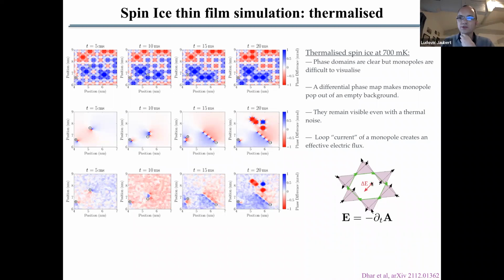To come back to Andre's question at the beginning, the magnetic charges are present, but the emergent electric field is still to some extent artificial. So it's an effective one, but as you can see in electron holography, it will give rise to a discontinuity of the phase map, a very sharp one, very clear one, that can be measured in experiments. And so that means that both the Dirac strings, the magnetic charges, and the fluctuations of electric field could be measured with electron holography a priori.